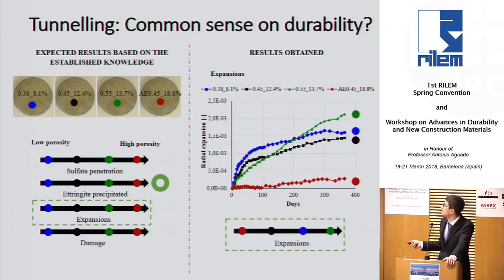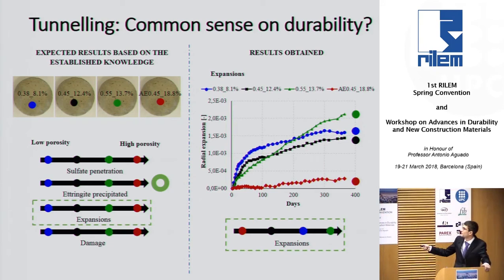There are different aspects that we have researched on this matter. And it's interesting to see that in some of the cases, the most porous specimens do not give the worst result. So this here is a very porous specimen that we have forced to be very porous, the red one. And here you see the expansion of different specimens, with the porosity on the right. And you see that the more porous one is giving less expansion, less damage than the least porous one. So sometimes more porosity doesn't mean that we have a worse material in terms of durability, right?